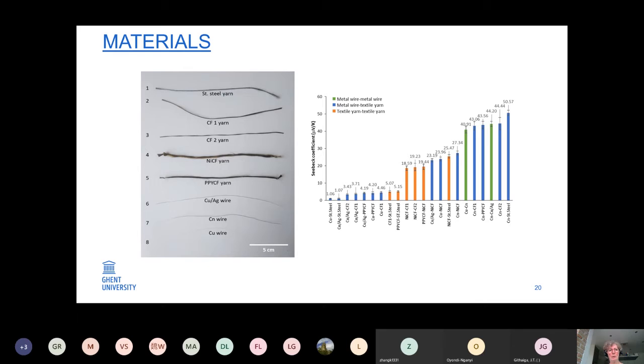And in the right graph, you can see the various effects that have been achieved. Most of them are pretty much in line with what could be expected based on the Seebeck coefficients of the material. And you can see for the textile materials, relatively good power outcomes can be achieved, although the constantan is the better one, but it's also not an easy material to work with, and it's not fully compatible with the textile processes.